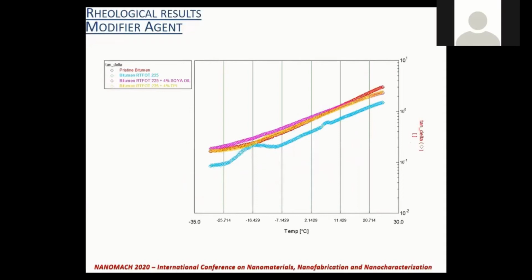In this picture, we show a semilog plot of the temperature ramp test at low temperature for all samples. Phase angle values at low temperature are quite scattered, owing to instrumental problems related to the high material consistency and therefore to the low measured deformation. In this case, we observed that both additives have similar rheological behavior to the pristine bitumen, while the aged bitumen is very hard in comparison to them. This also confirmed the rheological result at high temperature, and we were unable to distinguish the rejuvenating effect from the fluxing effect.